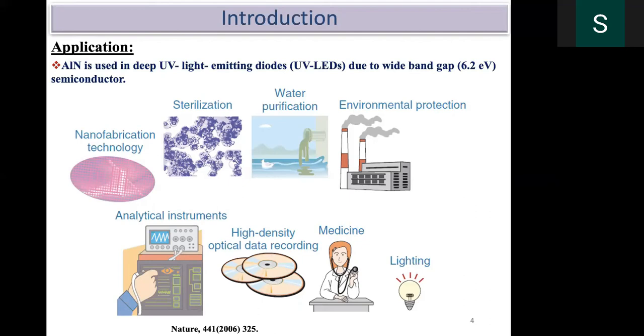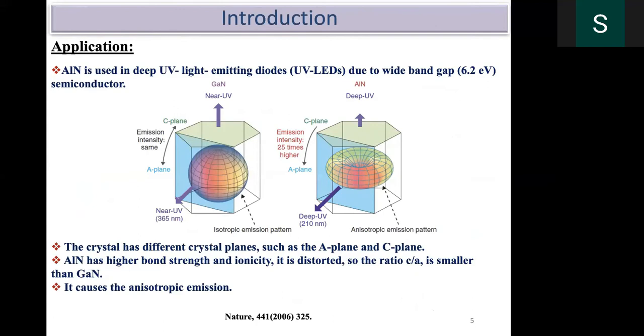Okay. Well, I just wanted to compare this gallium nitride and aluminum nitride. Already I told you gallium nitride is an LED material, and this is near UV, 365 nanometers, and you can get different colors by doping with indium or aluminum and so on. But when you compare the intensity of emission of gallium nitride with aluminum nitride, one more thing I missed here, it's 210 nanometers, deep UV, the light emission is different.